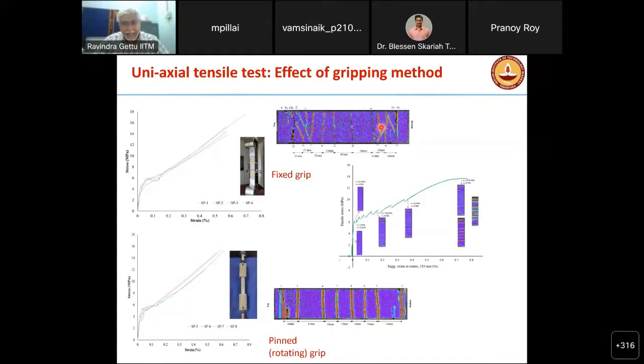So there is some random cracking, some inclined cracks. Whereas when the load is centered in the rotating grip, we have very sequential and systematic cracking. And if we design properly, you see that after the first crack, the load keeps on increasing. There is no plastification and there is an increase. And these are the images of when cracks start. Each drop signifies a new crack. Overall, the material shows hardening type behavior. So now we can design for hardening type response, and failure need not occur at very small strains like we do for normal concrete or fiber reinforced concrete. And we have now a system which is behaving as a strain hardening material.